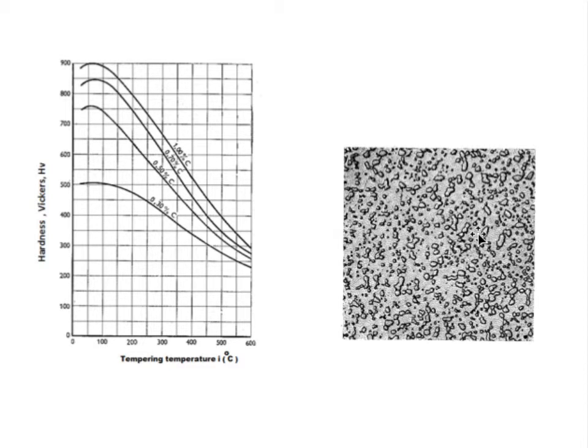So here we have a really ductile material. Interesting to note here is that this is an equilibrium structure for a long time at high temperature. And this is what we find in this two-phase region after a long time. The particles grow in size. Actually, if you also should start with a structure that contains ferrite and pearlite, that is, if we have got a structure that has cooled down slowly, we would also end up with the same type of structure. We would get this type of spheroidite, because after a while the lamella in the pearlite are going to be rounded and they're going to grow. So after a long time we get the same structure, as this is the equilibrium in this system at this temperature and at this composition. This is a structure then that is very suitable for machining and forming in cold shape.